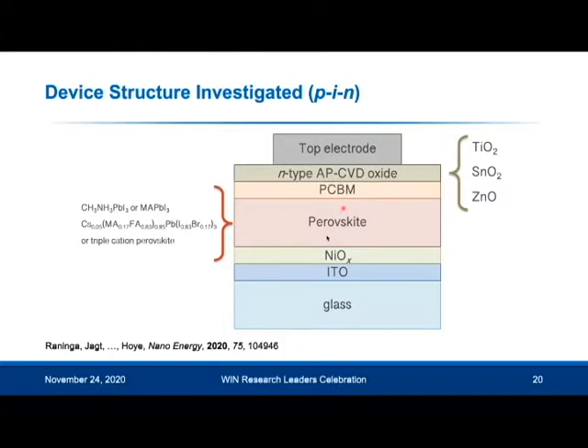And for the perovskite, I'm comparing two different perovskites. So the first is methylammonium lead iodide. Now, this is not very commonly used anymore, and the reason why we investigated this is for exactly the same reason, because it's very thermally sensitive. It's the most thermally sensitive perovskite. This would give us the worst case scenario. And I wanted to compare that against more state-of-the-art perovskites, which are these triple cation perovskites, where I'm mixing cesium, methylammonium, and formamidinium in the A site of the perovskite structure.